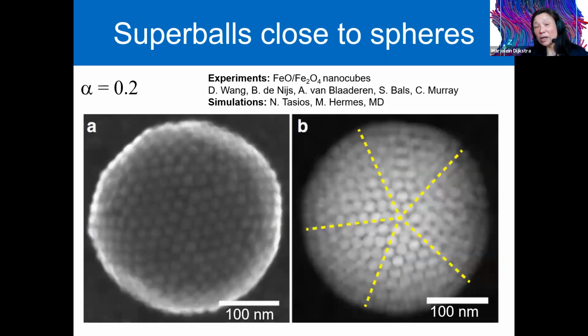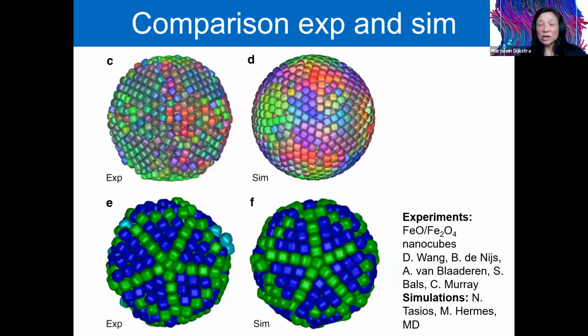We can also look at superballs that are closer to spheres. Then we find immediately that the clusters show this 5-fold symmetry. If we compare that with the simulations, we clearly see a very strong resemblance between experiments and simulation. And for cubes that are closer to spheres, you will find these FCC domains and these tetrahedral domains.